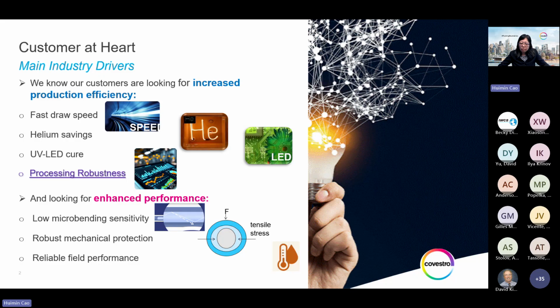And then, directly relevant to the ultra-low microbending design, we emphasized from very early on that it is very critical to mitigate the risk of ultra-soft primary coating defect formation, such as delamination and cavitation under external impact, such as in proof test. And the first paper at IWCS discussing high cavitation strength soft primary coating was our 2006 paper. And now, 20 years later, our new generation coating is truly demonstrating this ideal combination of superior microbending performance combined with robust mechanical protection against defects such as cavitation.